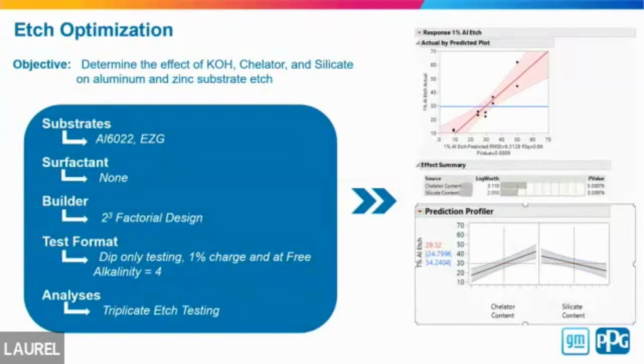Actually, something else that we have been optimizing for this technology, because as I mentioned, when you lower the temperature, you also impact all the performances. So that was screened through different DOEs, and then statistically we looked at the best formulation that provided the best HLD that we targeted at the time.